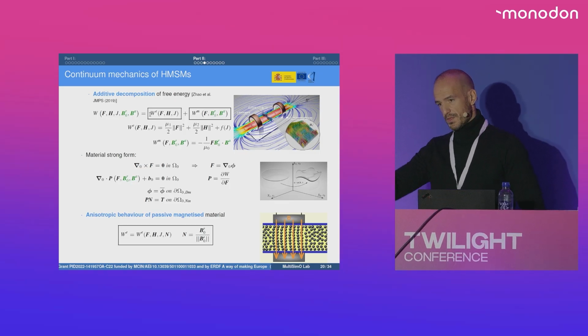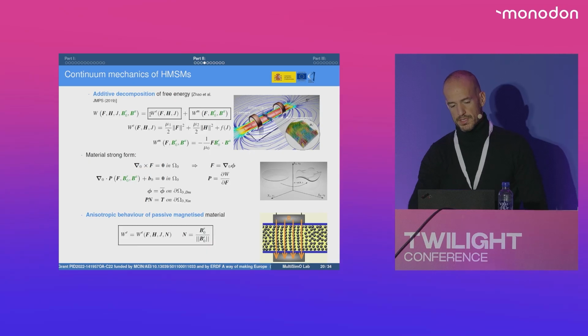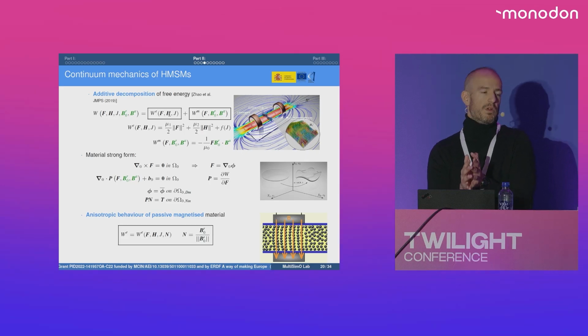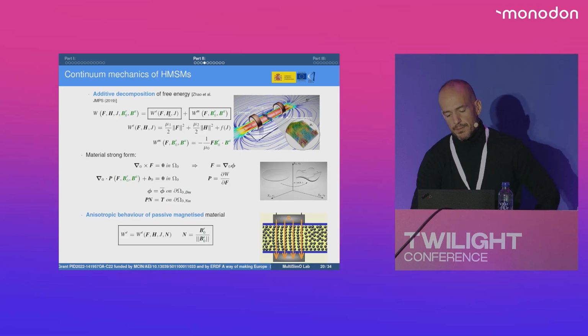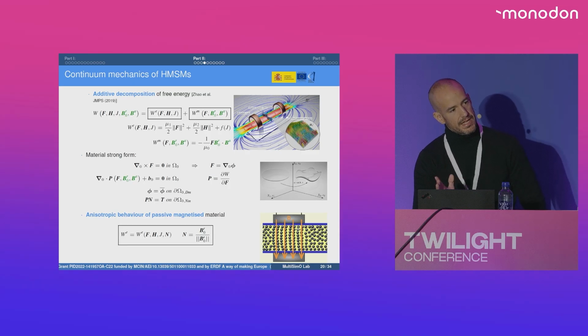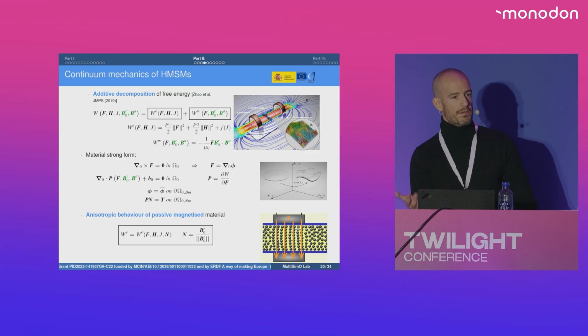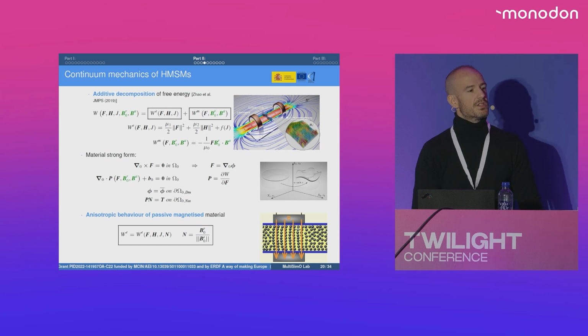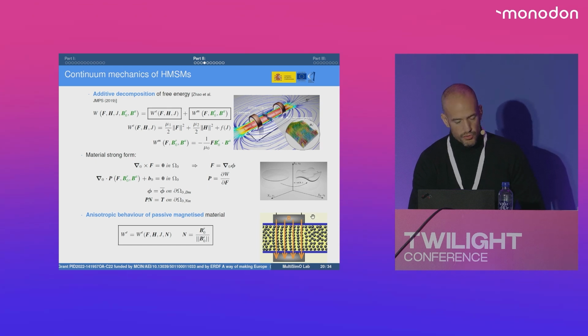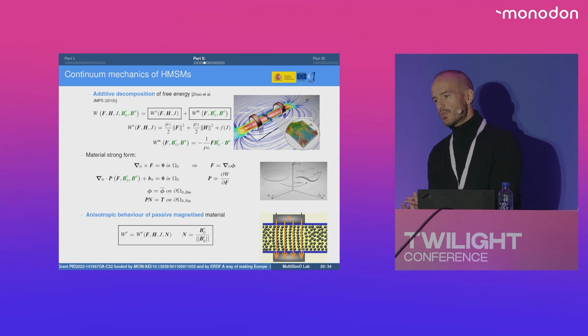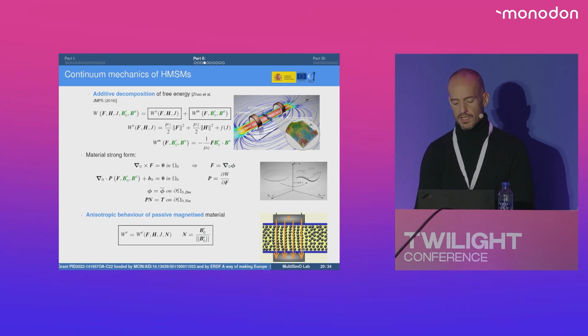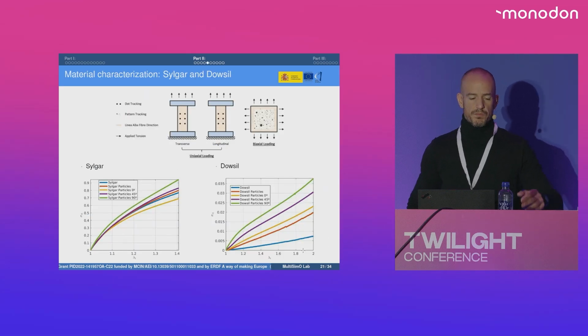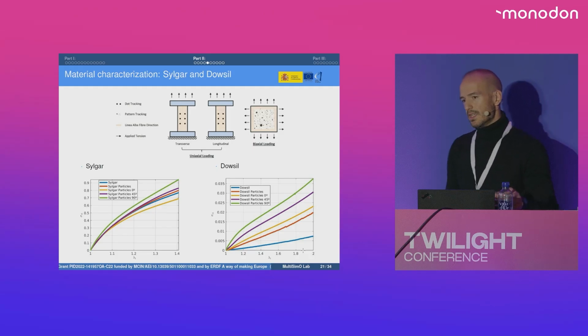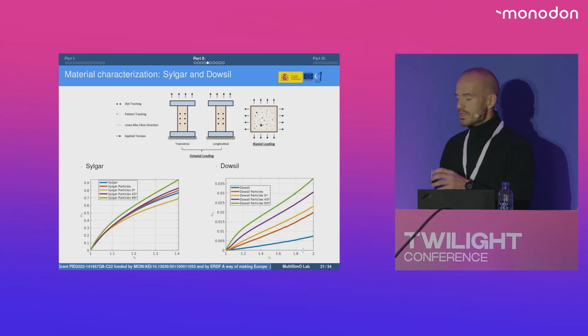Well, the relevant thing for this presentation, and this is the contribution from my colleagues at Universidad Carlos III, from Daniel, is that this passive response usually, when you have magnetized the material, the particles within the material are aligned. So the material is no longer isotropic, even when it's passive, when it's not actuated. It's transversely isotropic, actually. And you should include that anisotropy into the passive response of your material. And this is what they proved in the laboratory. So basically, they considered two materials, soft matrices, Dowsil and Sylgard.